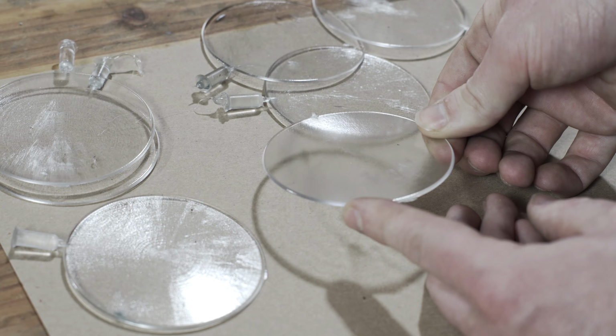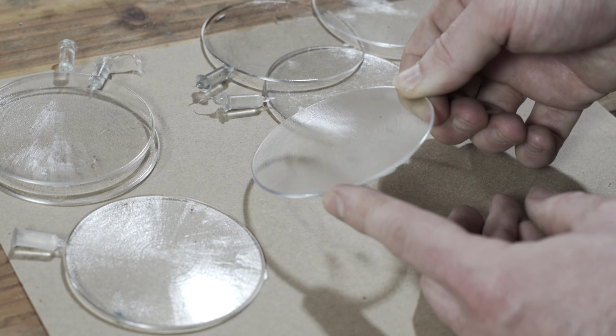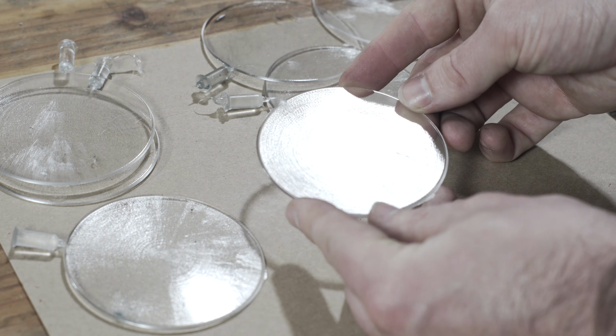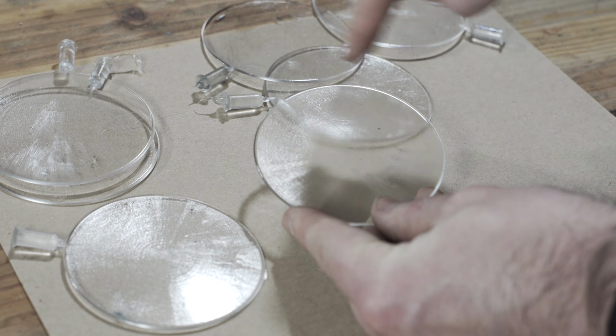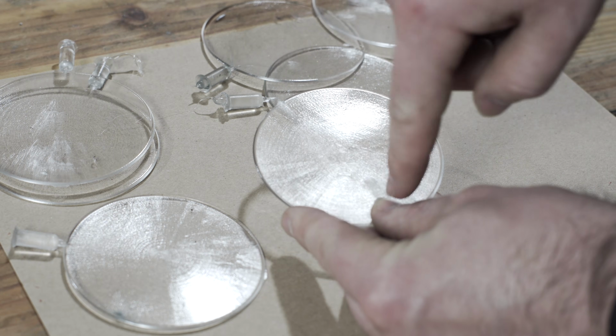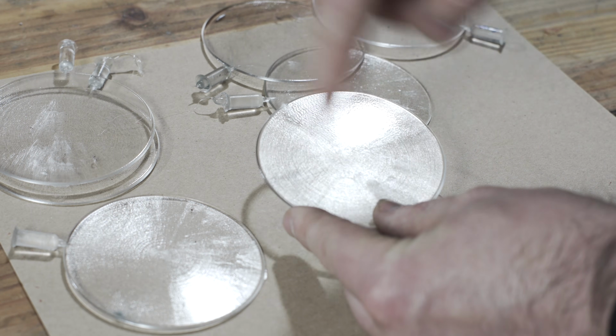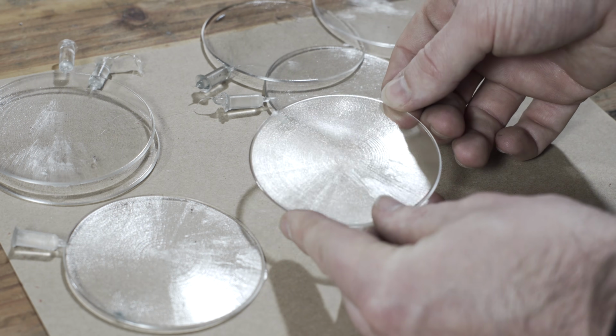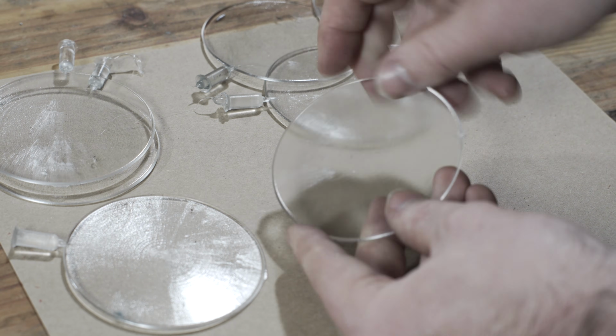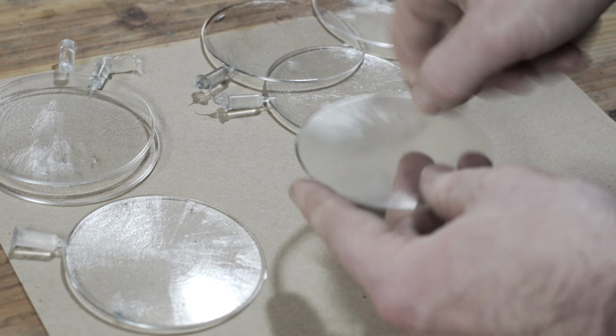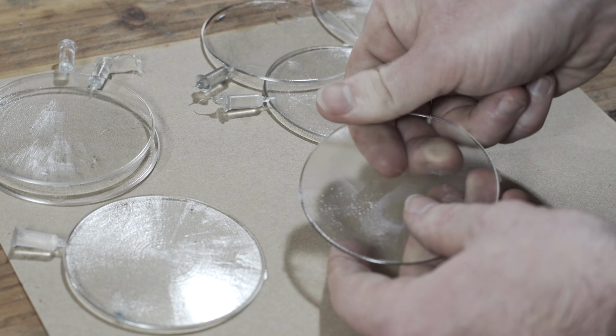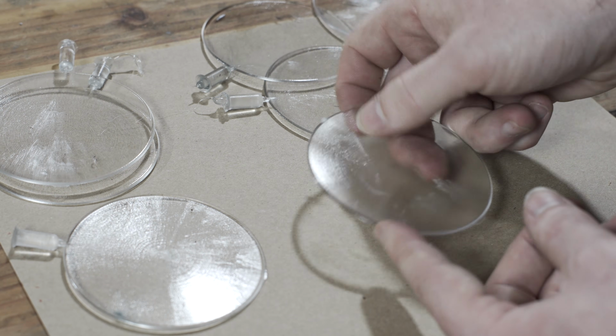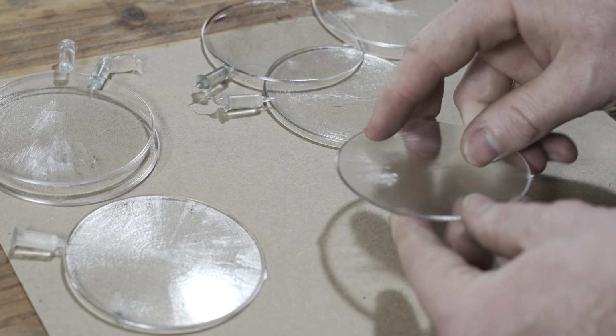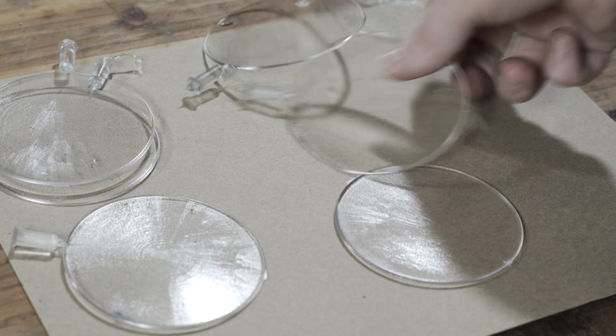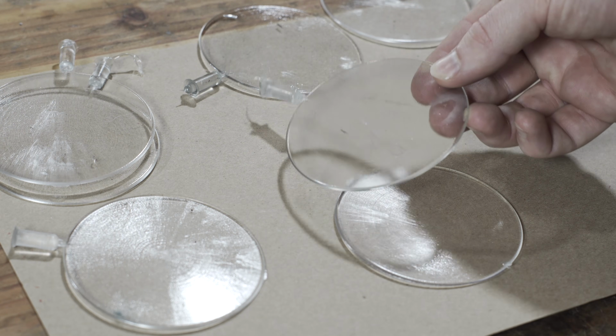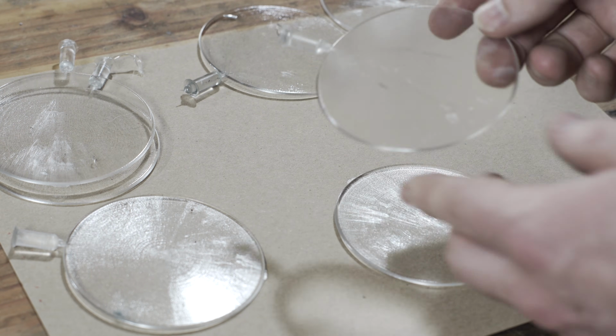If you can see in the reflections, it's hard since it's clear. Let's see if I can catch the light. There we go. So you can see essentially the machine lines, right? That's where the ball end mill was doing its circular path, and you can actually see that it was picked up in the plastic, which is pretty impressive, to be honest, because you can't really feel it. There's maybe a feeling of texture to it, but you can't catch a nail on it. So it's a relatively subtle feature, but it shows up really clearly when you look at it.